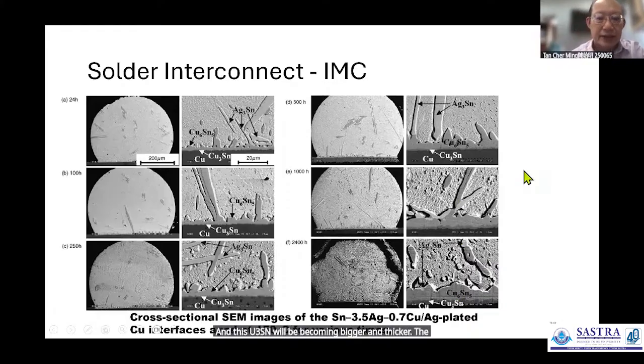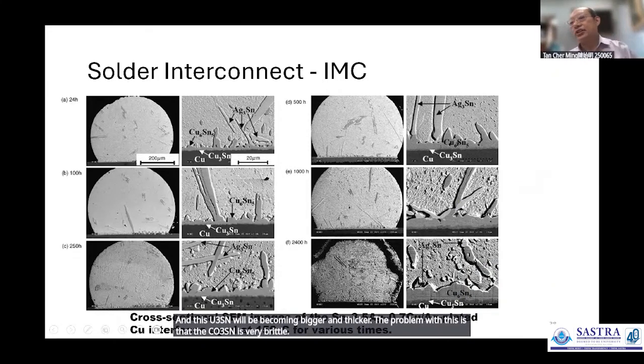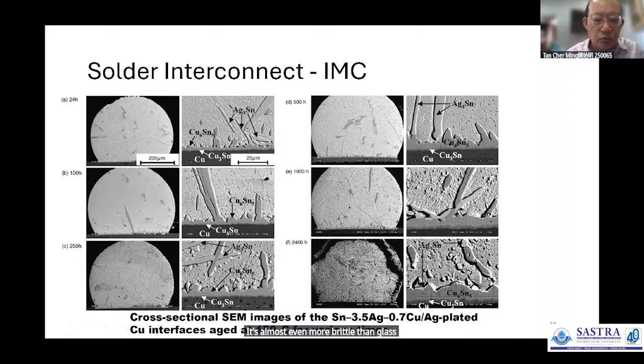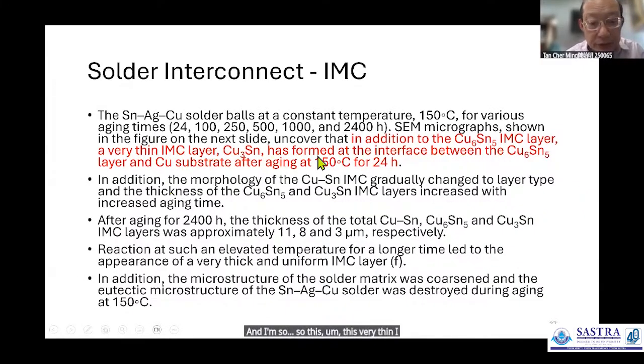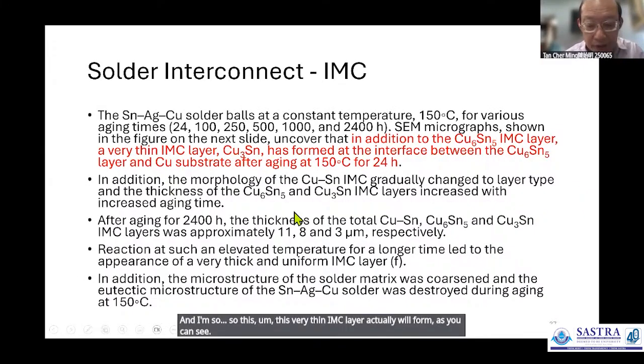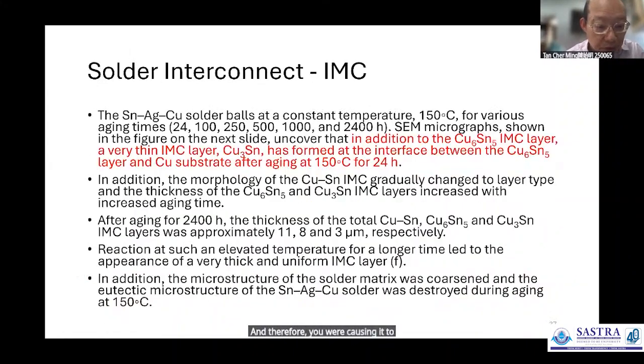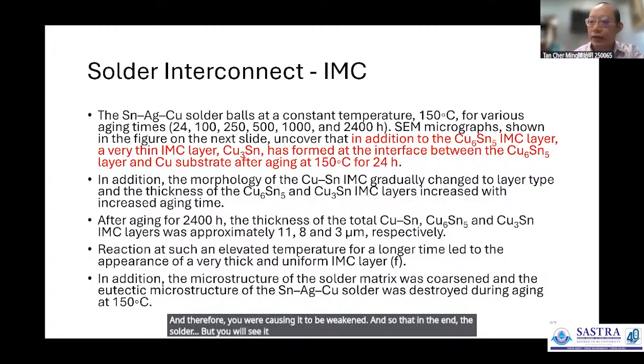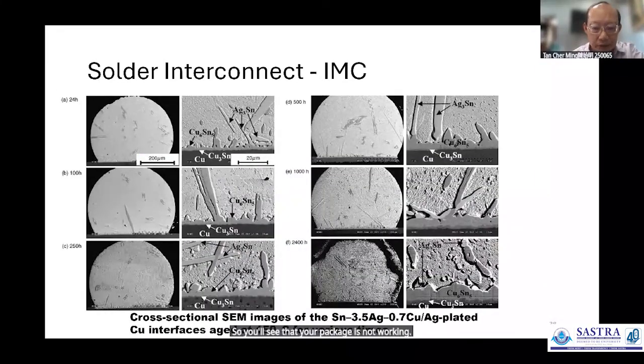The problem with this is that the Cu3Sn is very brittle. It's almost even more brittle than glass. So what it means is that when it is so thick and occupies the interface, when you drop it, it's almost like throwing a glass onto the floor, and therefore this whole thing will collapse. So this very thin IMC layer will form, as you can see, and you will cause it to be weakened, so that in the end the solder departs. But you won't see it because everything is inside the package. You'll just see that your package is not working because of this.